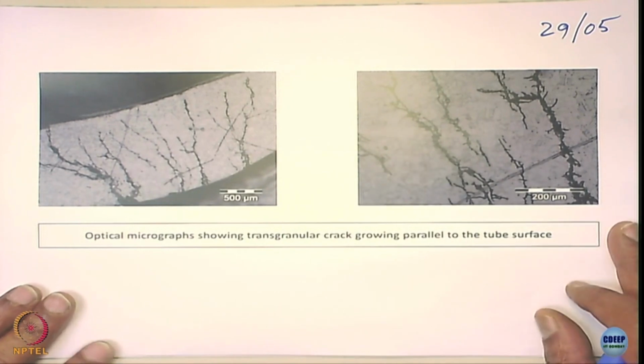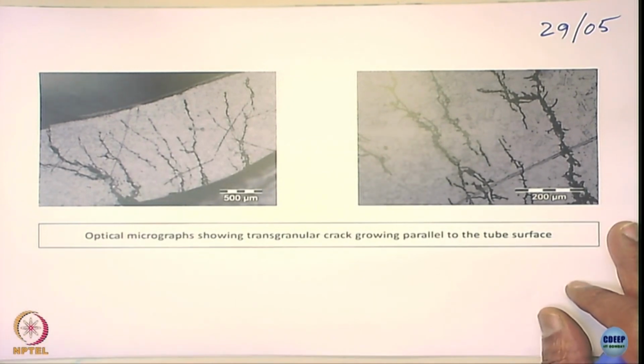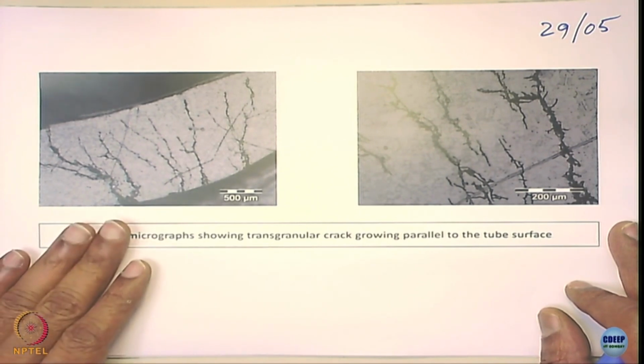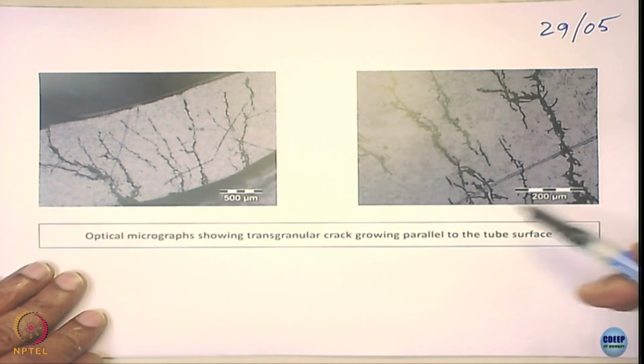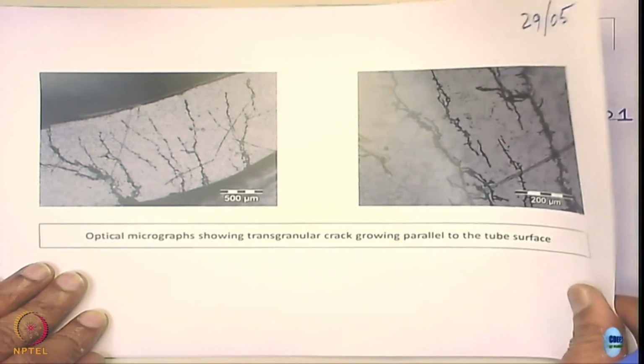Again, you see a kind of branching of cracks. This is one of the characteristics of stress corrosion cracking. If you do tensile testing, or if mechanical loading causes the failure, you only see one crack. The cracks are not branching at all. The crack morphologies we will discuss shortly. And this is also some kind of transgranular cracking taking place. Look at this in a scanning electron microscope in detail.